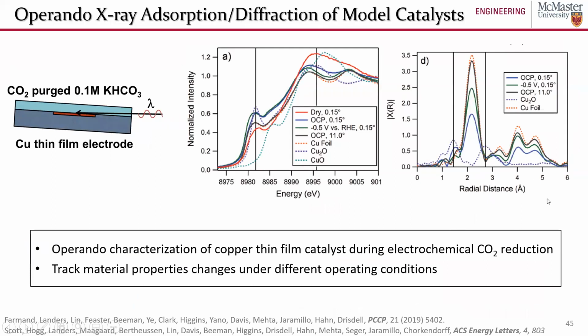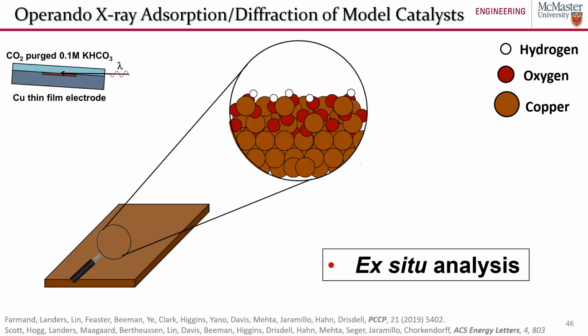So we flowed our electrolyte in with our CO2 reactant in it. We applied electrochemical potentials being controlled by the reference electrode, and we did X-ray absorption spectra measurements, and we did X-ray diffraction measurements. Once again, I don't want to dive into the weeds of these techniques, but essentially, if we go based on the literature, or on as prepared or post-testing catalyst characterization, if we were trying to understand the CO2 reduction process on copper, we would think that CO2 reduction occurred on metallic copper covered by a thin layer of copper oxide.